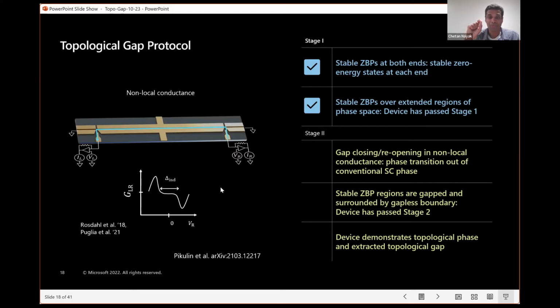But if the bias voltage is between the induced gap in the semiconductor and the parent gap of the superconductor, the charge that we push in stays in the semiconductor, can't go into the superconductor, and then it can only come out over here. So the derivative of I left with respect to V right is 0 at high bias, 0 at low bias, less than the induced gap, and non-zero between the induced gap and the parent gap. And so when the system approaches a phase transition, this region in which it's 0 shrinks as the induced gap goes down to 0, shrinks away, and then reopens. So we're looking for a gap closing and reopening in the non-local conductance. That's a phase transition out of the conventional trivial superconducting phase.